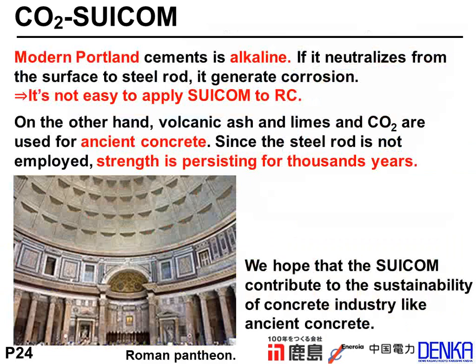Modern Portland cement is alkaline, so if it neutralizes from the surface with steel rod, it generates corrosion. Therefore, it's not easy to apply CO2-SUICOM to reinforced concrete. On the other hand, volcanic ash, lime, and carbon dioxide were used for ancient concrete. Since steel rod is not employed, the strength has persisted for thousands of years. So we hope that CO2-SUICOM contributes to the sustainability of the concrete industry, like ancient concrete.